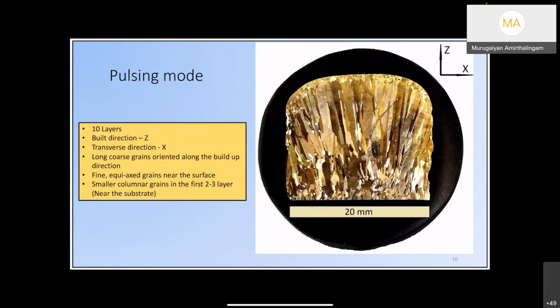So when you look at this deposition, obviously this is not good, isn't it? And this is what primarily happens in any additive manufacturing, especially when you have a laser and powder or laser and wire deposition. You are depositing on a substrate. The substrate is at a much lower temperature. It is technically at room temperature, isn't it? If you are cooling with effective heat transfer, when you drop on a layer of molten liquid, the temperature difference between the bottom surface and top surface would be huge. The top surface will be well above melting point, whereas the bottom surface we expect to be in a solid state, much lower. Therefore, the temperature difference will be much higher, and so we expect planar solidification.